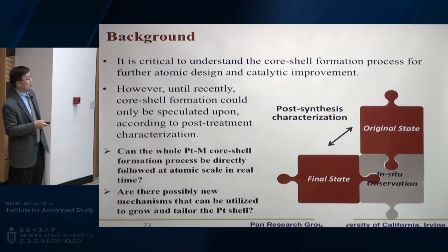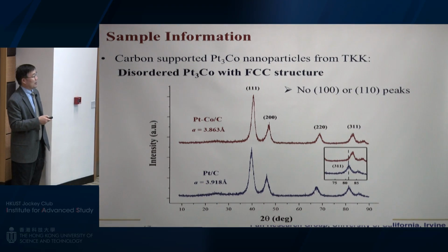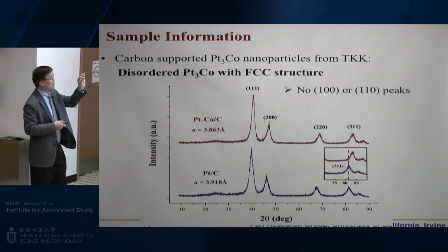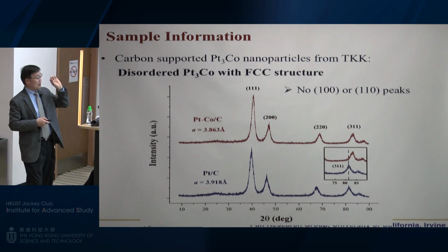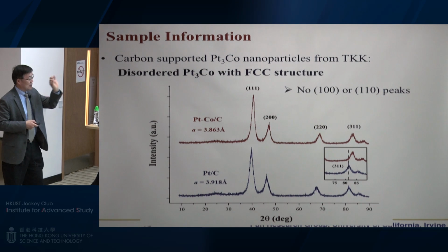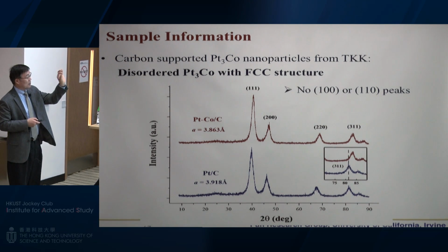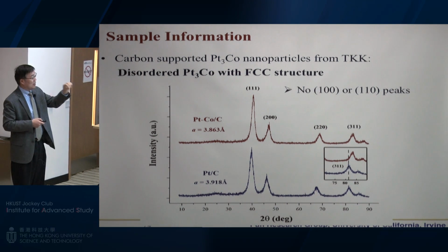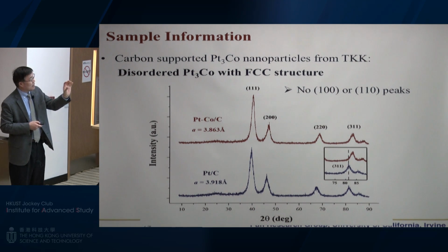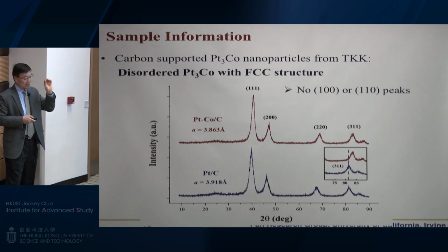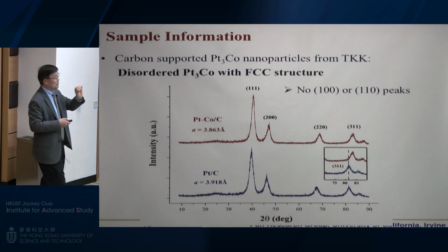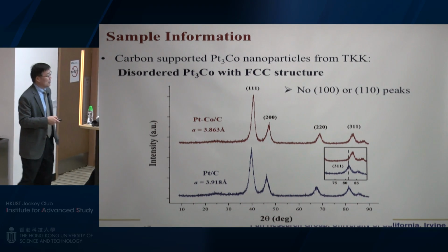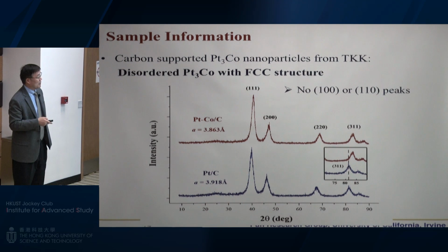And we try to study this material with disordered platinum cobalt. First we see how this disorder to order transition happens. And then after it transforms into the ordered phase, in the oxygen and hydrogen atmosphere, we look at how the structure changes. This was the purpose of our study.